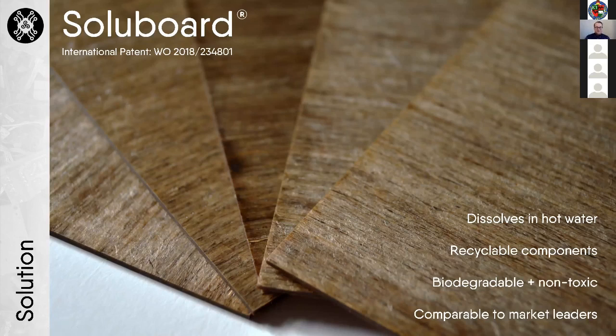The backbone of the Recollect project is Soluboard. Typically PCBs are made of fiberglass and epoxy resin, and when recycled they are incinerated to recover precious metals. We've developed Soluboard that allows PCBs to be recycled in a much cleaner way. Soluboard PCBs will be non-toxic, recyclable, and fully biodegradable, produced using natural fibres as opposed to glass fibres. The substrate can be dissolved in hot water, allowing you to remove the natural fibres, compost them, and recover the components for more efficient and economic recycling.